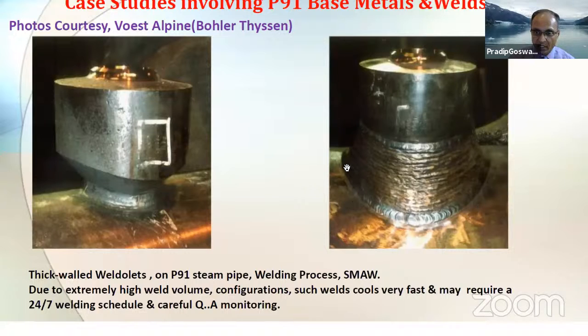Typically for these weldolets, one has to be very careful about toe cracking, which is very common for these, leading to failures down the road from many industry experiences. But this is a common design which is adopted by ASME B31.1 code. And when welding of these weldolets to the main steam pipe is concerned, one has to be extra careful because of the shape, the groove size, and the ultimate weld volume involved.